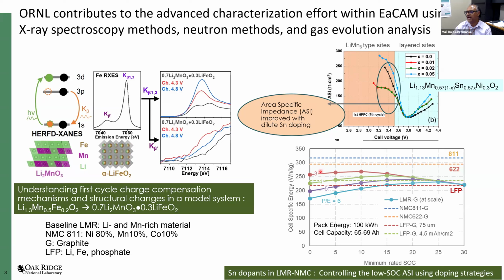However, there are a lot of challenges with this material, and one of the specific challenges that we are trying to address is how we can control the low state of charge area-specific impedance, and we show that we can do that using doping strategies. The first one, so I'll first start off with this area, which is development of lithium- and manganese-rich materials.